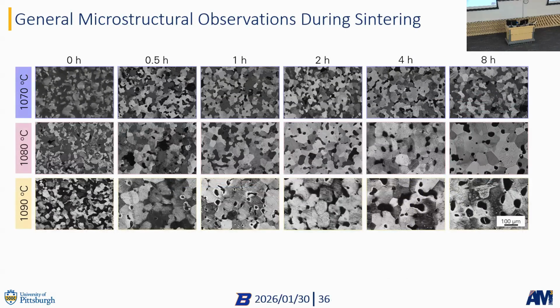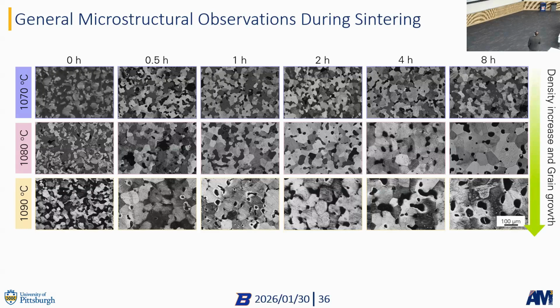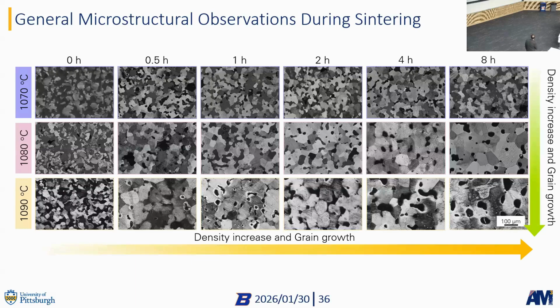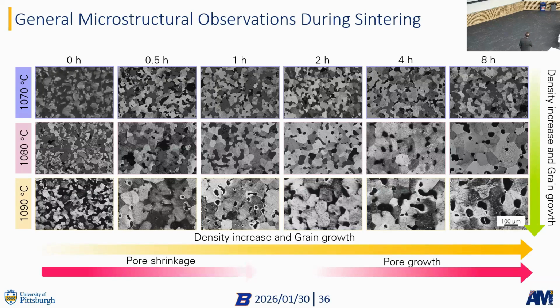Now we wanted to figure out sintering mechanisms again. How can we optimize the pore size so that our grains are disconnected, and make really large grains at the same time? For that, we again had a lot of undergraduate students in our lab that cut and polished a lot of samples. What we found is fairly obvious: with increasing temperature, we increase density and grain growth. With increasing sintering time, we also increase density and grain growth. But one interesting thing was, with increasing time, we saw pore shrinkage. The pores got smaller to some point, and then the pores coalesced again and actually grew. But we also eliminated some pores. So we can use this graph to identify the optimum pore size and grain size for these structures.